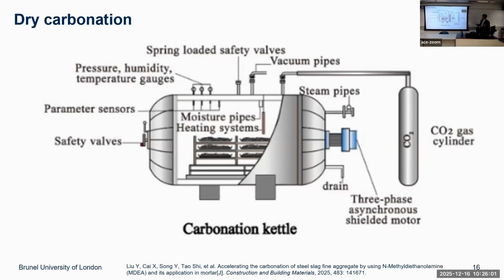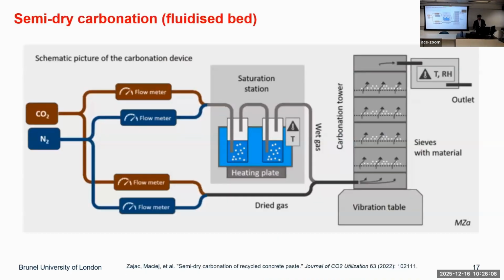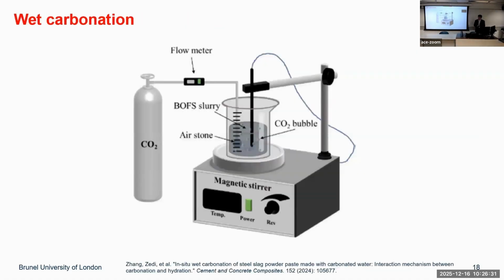Later on, we'll talk about the water factor controlling the efficiency of carbonation. And semi-dry: the particles go down with the gas flow, so you make sure that the particles are exposed so that all the surfaces get a chance to connect with the moisture and carbon dioxide. This is called semi-dry. Then wet carbonation.